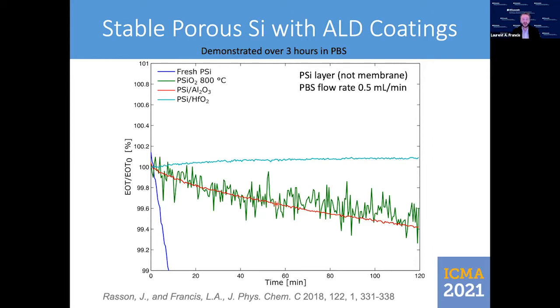to the lower noise. And finally, we can also, by atomic layer deposition, coat different materials, such as in the blue marine curve here, have hafnium oxide, in which case we have a very, very stable signal and the same noise level as in the case of the alumina.